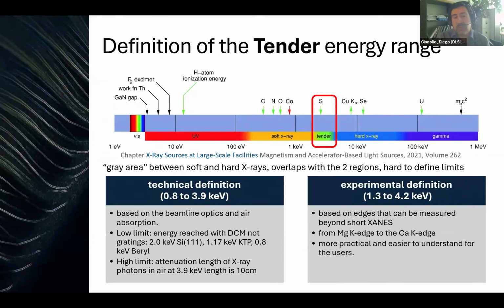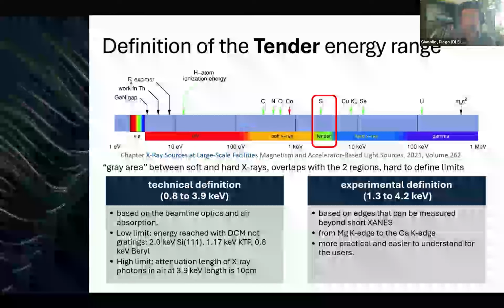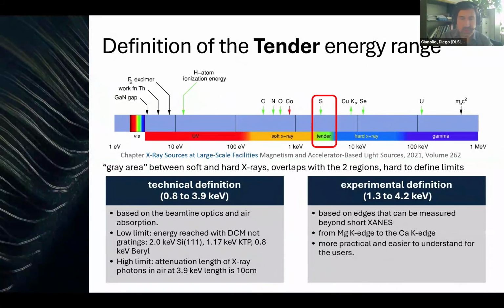The experimental definition is more based on the quality of the data that we can obtain. So when you go to soft X-ray, normally you collect very short XANES, as they are more commonly called for soft. While if you are in hard X-rays, you are normally interested in collecting a longer energy range and get a good XANES. So if we base this definition on where we can measure something that is more than just a very short XANES, then we can have as two limits the magnesium K-edge and the calcium K-edge.